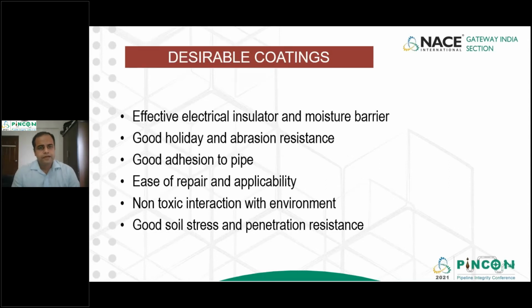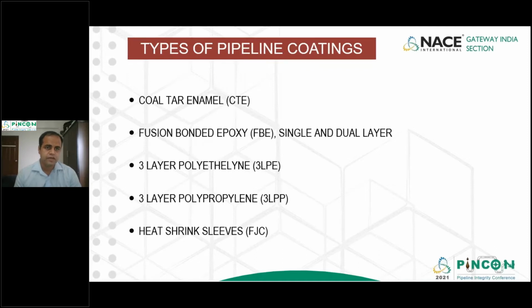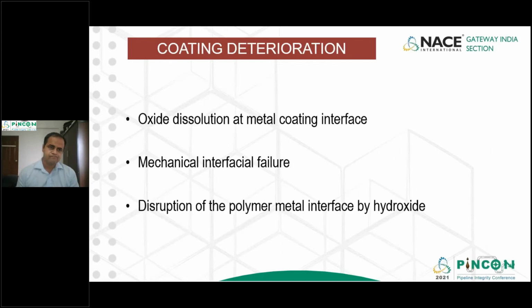Dear all, what desire do we have when we buy coatings for our pipelines or apply them? It needs to be an effective electrical insulator, with good holiday and abrasion resistance, good adhesion to pipe, ease of repair and applicability, non-toxic interaction with environment, and good soil stress and penetration resistance. Types of pipeline coatings mostly involve coal tar enamel, fusion bond epoxy, 3-layer polyethylene, 3-layer polypropylene, and heat shrinkable sleeves.